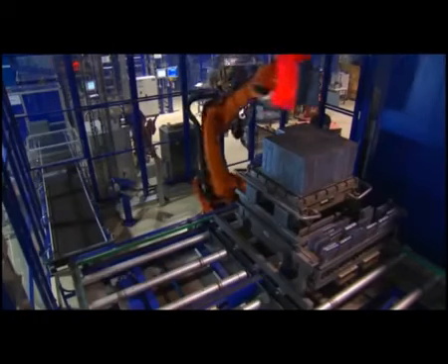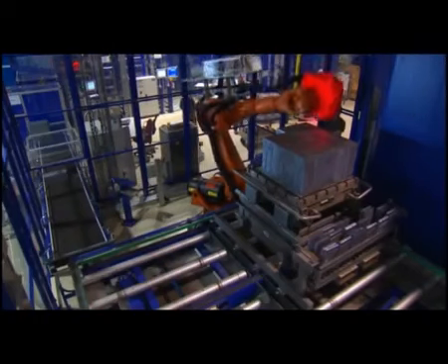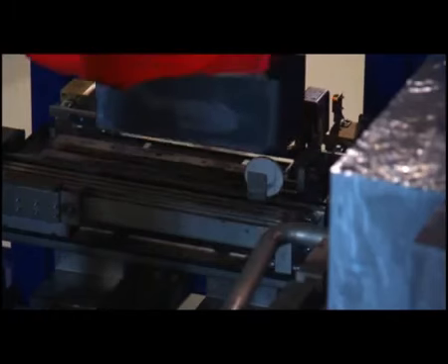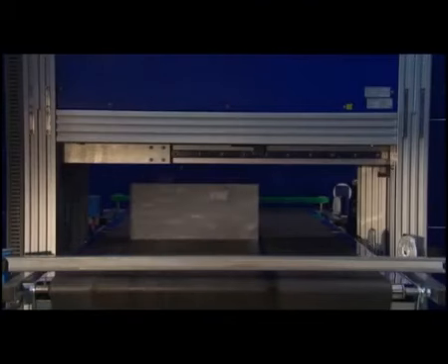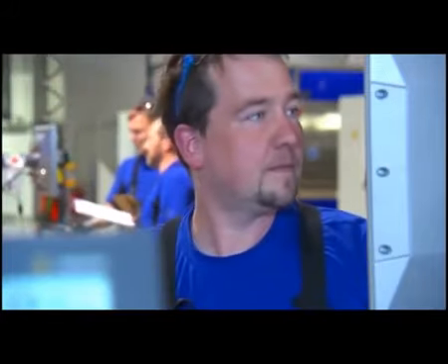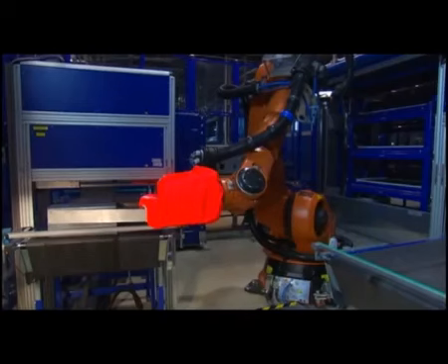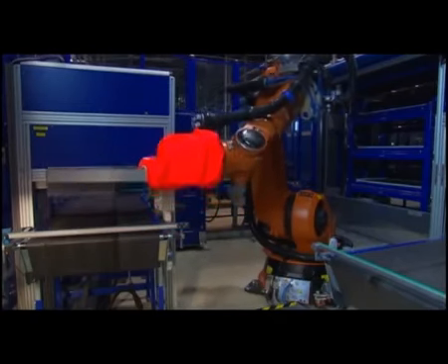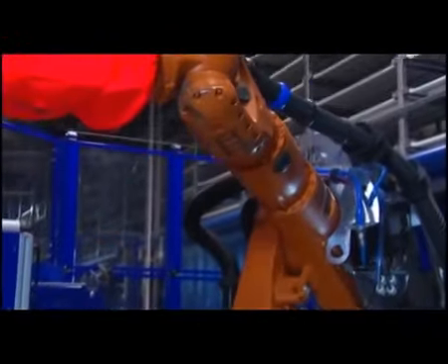15 minutes later, a robot picks up the bricks one by one, measures their geometric parameters, and passes them on for marking. High-tech measurement devices weigh and measure the silicon bricks and scan them using infrared rays to determine the quality of the silicon crystals. Short and efficient routes, these are the defining features of our wafer production workflow.